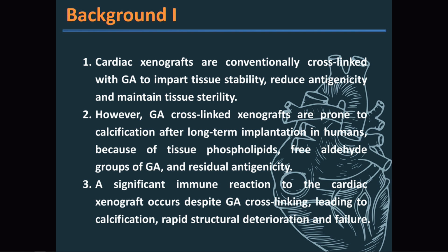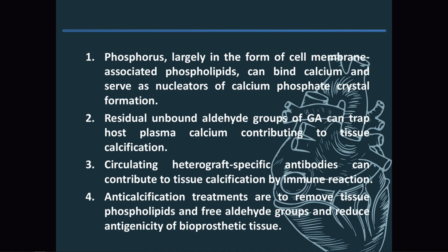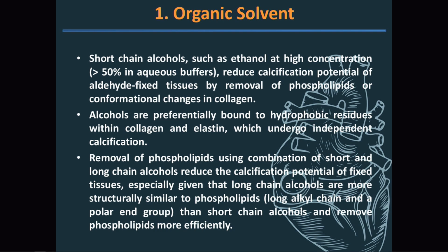The cardiac xenografts are conventionally cross-linked with glutaraldehyde to have tissue stability and reduce antigenicity. However, the cross-linked xenografts are prone to calcification after long-term implantation in humans because of phospholipids, residual unbound aldehyde groups of glutaraldehyde, and immune reaction.